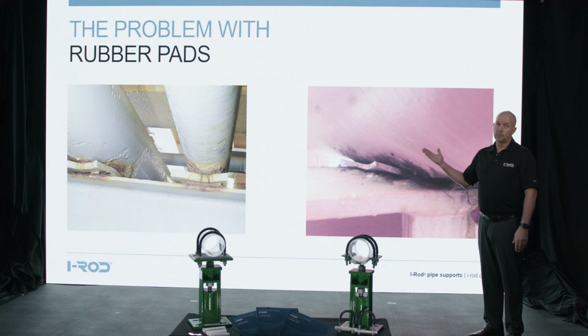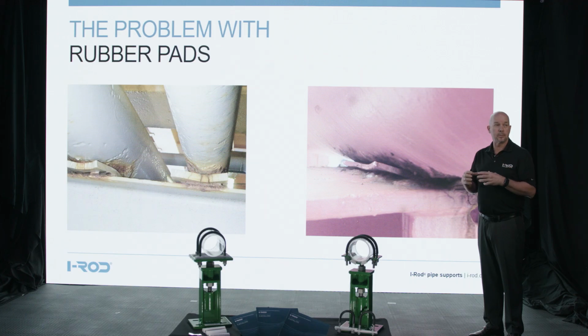Here's some examples of what rubber pads look like after some time in the field. You can see here on the left there's some really thick rubber pads that have been installed underneath the pipe. And you'll notice in the image that there's those dark lines or cracks in the rubber. That happens over time. The rubber becomes more porous and traps and holds a lot of water. And you can see that that whole area that's in contact with the pipe, lots of corrosion's happening. It actually is accelerating the corrosion issue because there's more water in that location than there would be without the rubber.